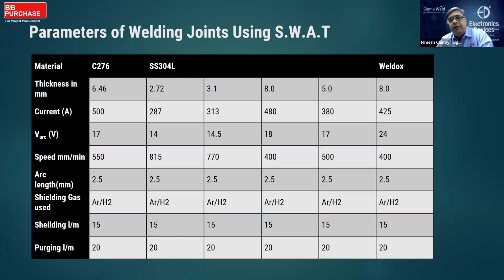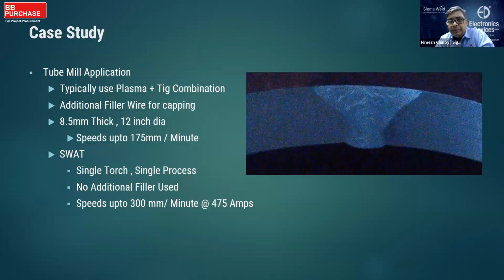These are speeds that we have tabulated. For Hastelloy, they are about 550 millimeters a minute for a 6.5 millimeter thick plate. For stainless steel, we've done all the schedule 10, that is from 2.72 to 8 and 10 millimeters. And you can see the speeds gradually going up. So at 8 millimeters, we are at about 400 millimeters a minute. And for Weldox, we are still doing it at about 400 millimeters a minute with 8 millimeter thickness.